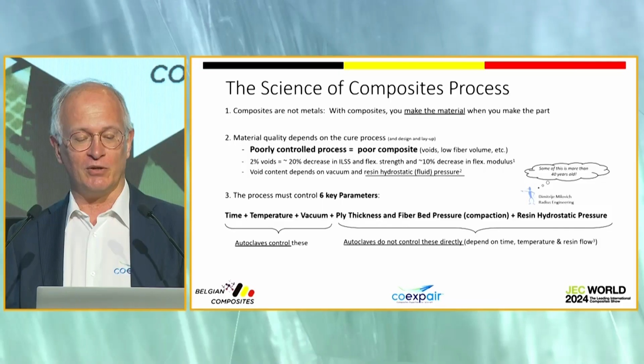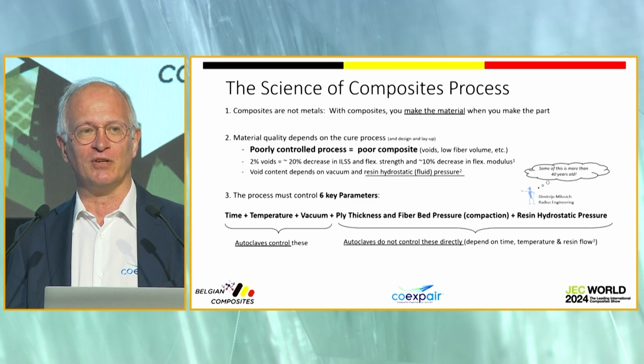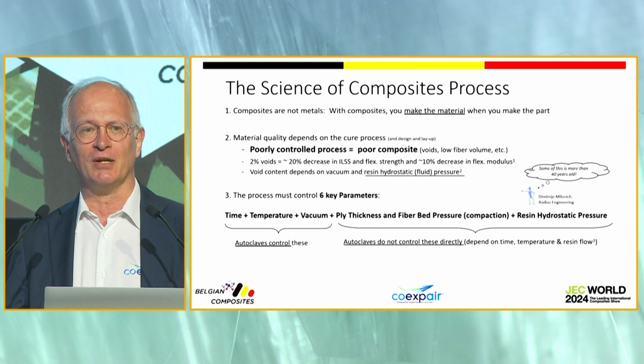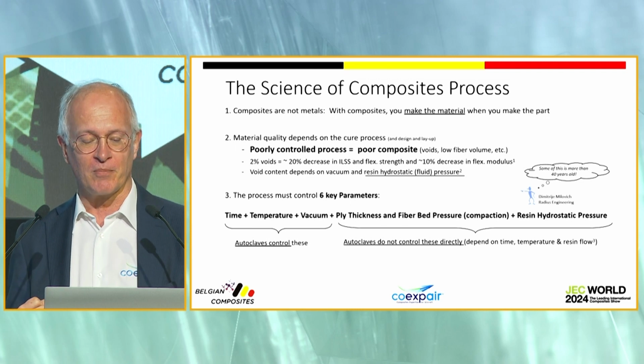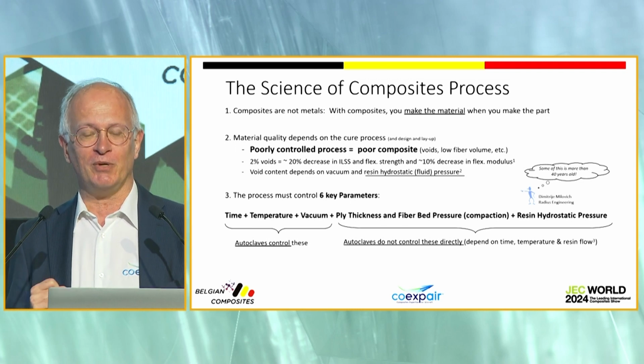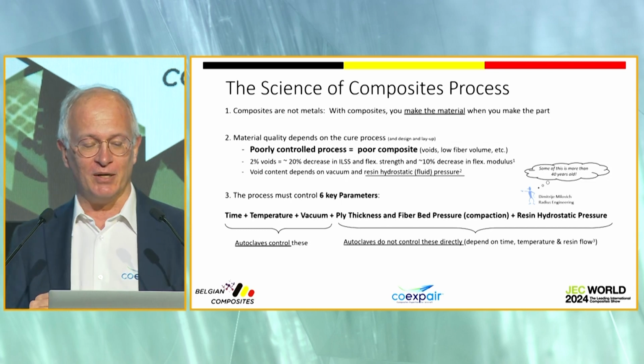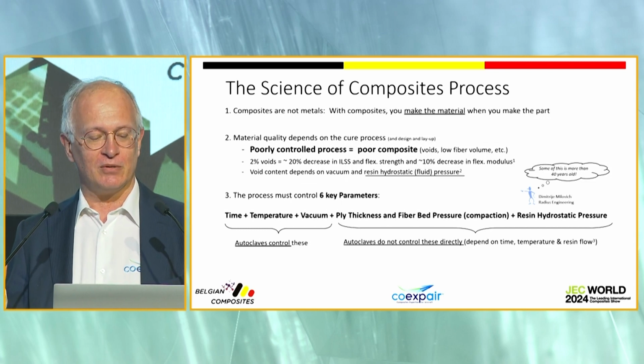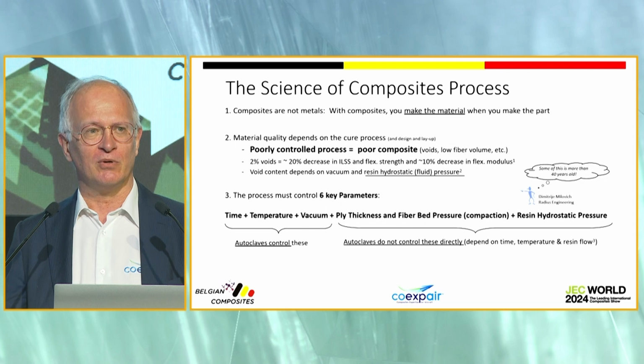One key point is porosity. To avoid porosity in a part, you need really to control the resin hydrostatic pressure, and you need to control it independently from the other parameters. The 6 key parameters Dimitri likes to remind: time, temperature, and vacuum.